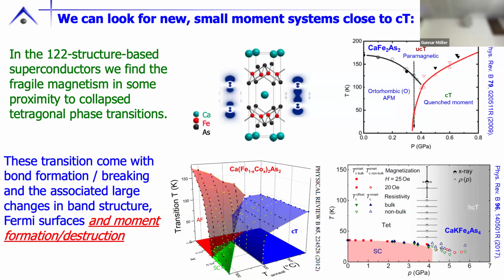So this is something that we found in CaFe2As2 when we discovered the material and applied pressure, but this is a type of transition that Hoffman was well aware of in the ThCr2Si2 materials, in some of the germanides and silicides as well as phosphides. Now, you can perhaps see more dramatically here in doped CaFe2As2 with a little cobalt, we can again see that the collapsed tetragonal phase kills antiferromagnetism, kills superconductivity. In the calcium potassium iron 4 arsenic 4, a quaternary superconductor, we can see our superconductivity. And when we hit a half collapsed tetragonal, we lose all superconductivity and magnetism.